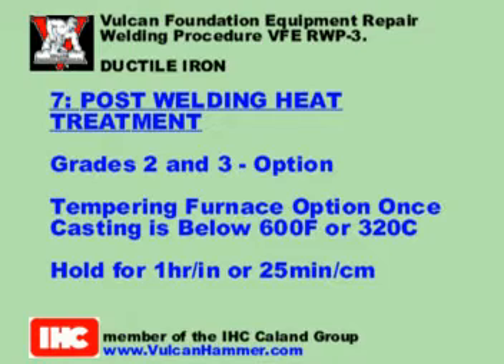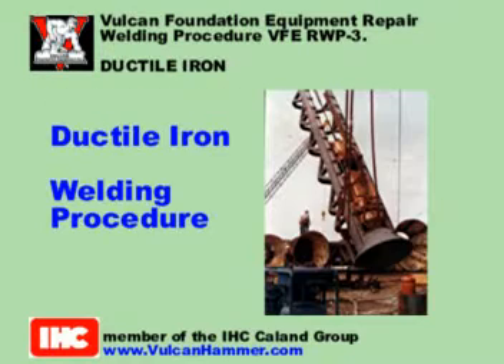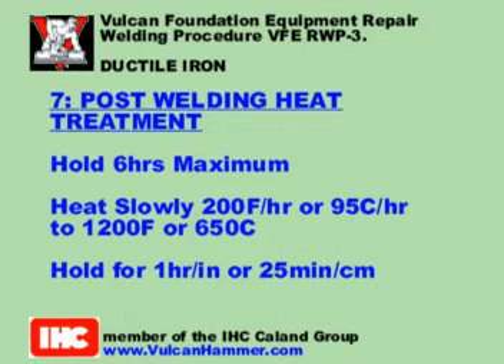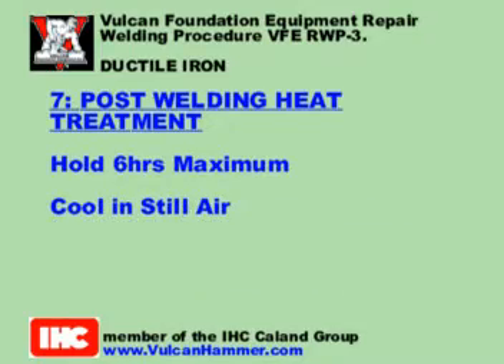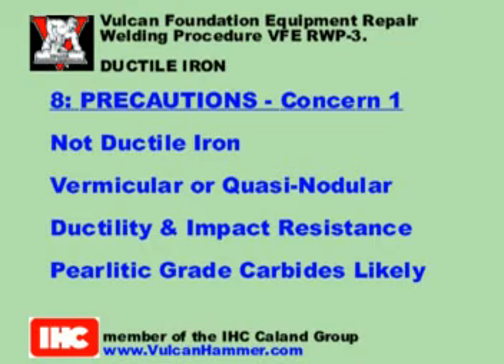Cool in still air. When the temperature of the casting is below 600 Fahrenheit or 320 Celsius, it may be placed into a tempering furnace, soaked at 600 Fahrenheit or 320 Celsius for 1 hour per inch or 25 minutes per centimeter, 6 hours maximum, and heated slowly 200 Fahrenheit per hour or 95 Celsius per hour to 1200 Fahrenheit or 650 Celsius. Hold at temperature for 1 hour per inch, 25 minutes per centimeter, 6 hours maximum, and cool in still air. Section 8, Precautions.